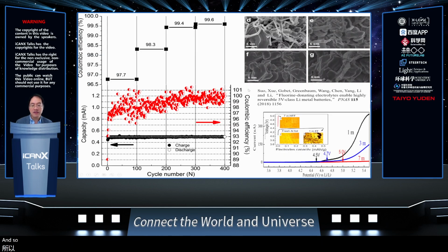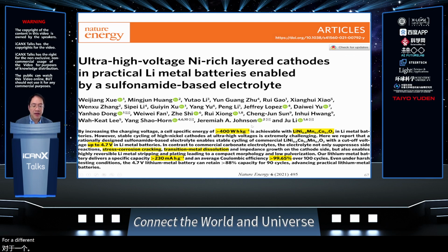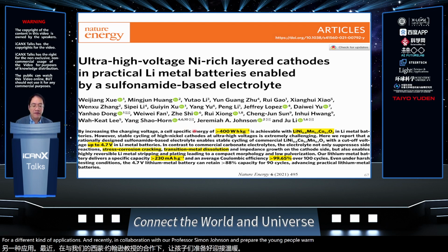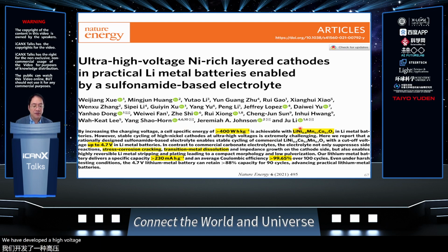And so we have shown that with more and more fluorine in the electrolyte, we can have better lithium metal deposition morphology on the lithium metal side, but also on the cathode side, we can sustain up to 5-volt without corroding the aluminum current collector. And so now we're using these automated experiments to design new electrolytes for different kinds of applications. And recently, in collaboration with Professor Jeremiah Johnson and Professor Yang Shao-Horn, we have developed a high voltage electrolyte for this NMC 811 cathode, which allows us to charge up to 4.7 volts.